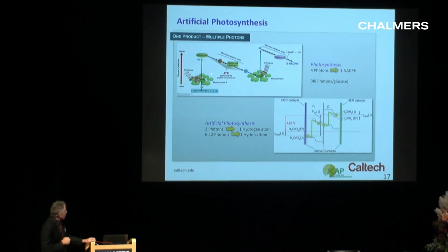And charges are transferred between these, and so we excite over two to get enough potential here to create the proton equivalents that make NADPH from NADP. Similarly, in inorganic structures, the tandem allows us to absorb both the red and the blue parts of the solar spectrum and convert the energy more efficiently, like the tandem I showed you. But they also, importantly, build the voltage, which allows us to span the energy difference between the energy required to oxidize water on one side, on the anode side, and to reduce water to hydrogen on the cathode side.